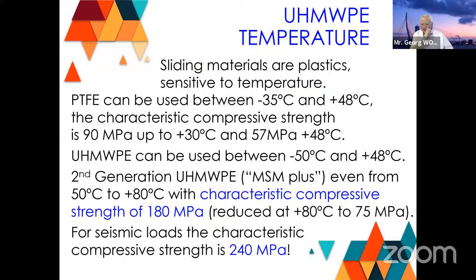Of course, you can use Teflon for much higher temperatures. I mean, in your kitchen, you will have some pans with the Teflon, and you can heat them up to 300 degrees. But the tests for the sliding materials were just in this range. And the characteristic compressive strength is 90 megapascal up to 30 degrees, and then it goes down, and at 48 degrees, as this limit, it's still 57 megapascal.